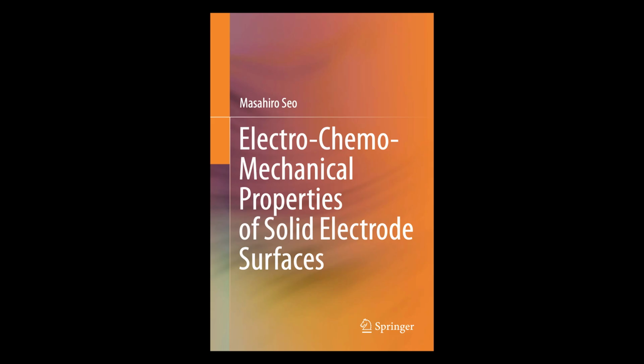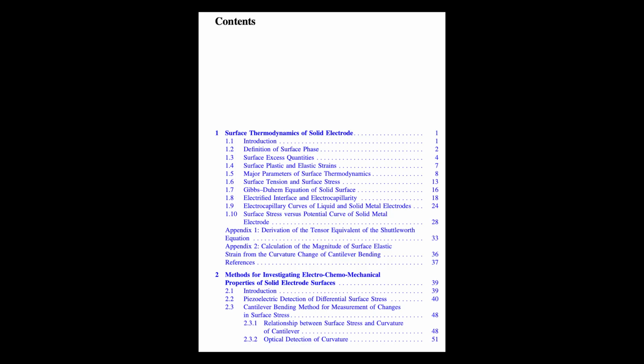Exactly. And it's been used on passive metal surfaces too, like iron sitting in a borate solution, which forms a very thin, protective passive film. Those studies show that even an extremely thin passive film, just nanometers thick, can significantly influence the measured hardness. Wow. A film that thin makes a difference you can measure. Definitely. And you can even see the effect of surface treatments. For example, putting a chromic conversion coating on passive iron changes its nanomechanical properties in something called the work ratio, which relates how much the deformation is elastic versus plastic. It's incredible how much influence such a tiny layer can have on the overall mechanical feel of the surface.